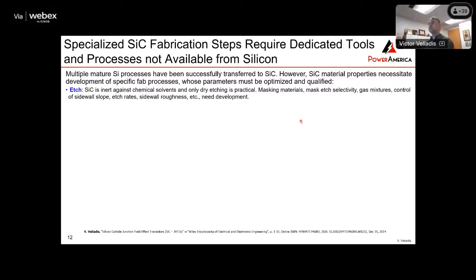So what are those? When it comes to etching, silicon carbide is inert against chemicals, and only dry etching is possible. So you cannot do the wet etch that's available in silicon, and it's a very hard material. So if you just use resist, which is the common in the silicon world, you're going to be eating away the resist faster than you're etching the silicon carbide. So you need to have the right masking materials. The selectivity is very important, and the right gas mixtures and control in order to get the right sidewall, minimize sidewall roughness and get the right profile. There's also substrate thinning, because the substrate is a very big portion of the resistance of the silicon carbide device. So we want to thin the substrate to reduce that contribution.